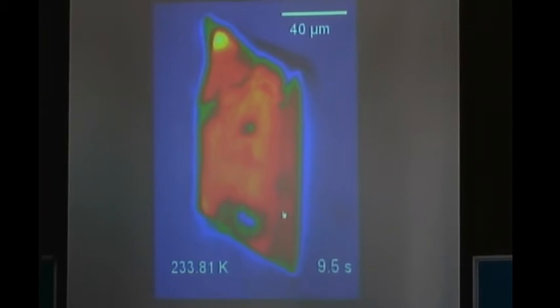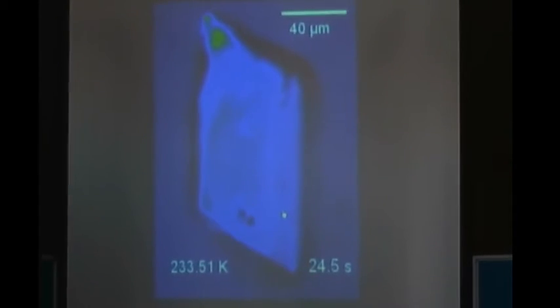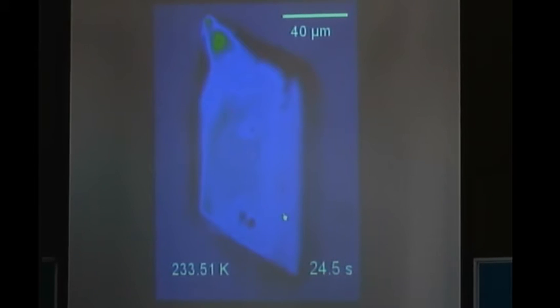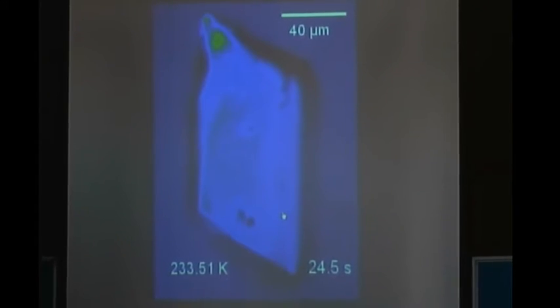You see? So the direction of the nucleation and growth is inverted. It started through the defect, and then it completely inverted the direction. At the beginning, we have our propagation in this direction. Because we put a defect here, we changed completely the propagation. That means that the nucleation and growth of the spin switching on the crystal can be modified by applying artificial defects. We are also working now on the form and the shape of the nanoparticles, to see that we can have very nice physical properties, very nice kinetic properties. We can play with this nucleation and growth, and we can even control it by applying some intelligent defect in the system. This is a very important point.